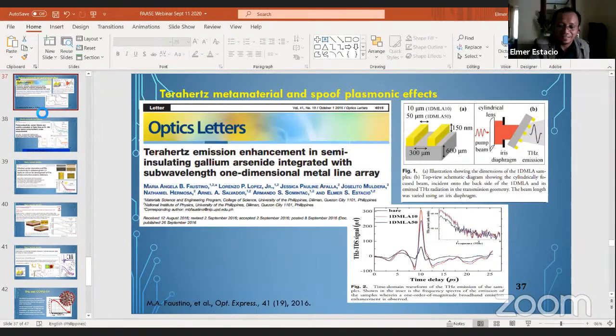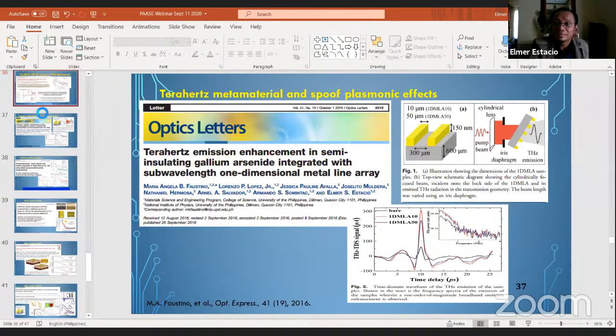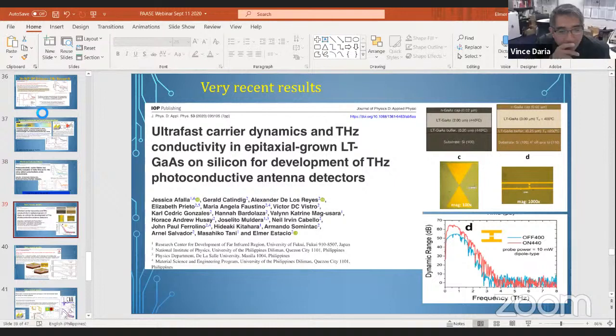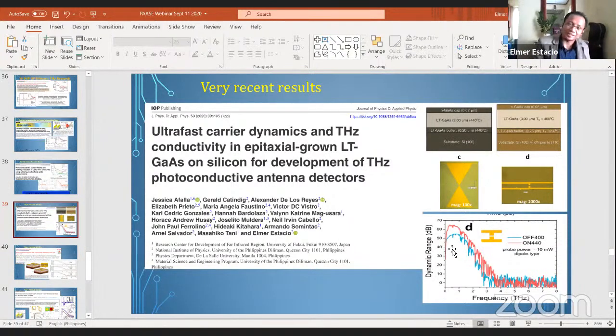It doesn't mean anything. It's a plotting error, if I may say so. No, this is a mathematical artifact of the Fourier transform. So please excuse that. There's no such thing as 0 frequency. This is a Fourier transform error and plotting carelessness. But people who do terahertz work actually do this, and we get away with it. But terahertz radiation coming from these types of photoconductive antennas would typically have a lower frequency limit of about 250 to 300 gigahertz. Around here.